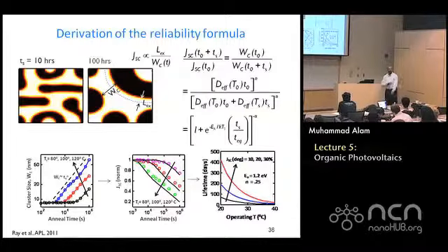Now, of course, this is not the end of the story. People are very clever. What they have done is that right after processing, there are photo cross linkers in here which essentially, just before they ship it, they zap it with X-ray so that these photo-cross linkers create a container, sort of a network, which binds them in place. Now they cannot phase segregate when they are in Arizona sun. They want to, but this network of traps then keeps them in place. That is how they have recently gotten 3 to 4 years projected lifetime.